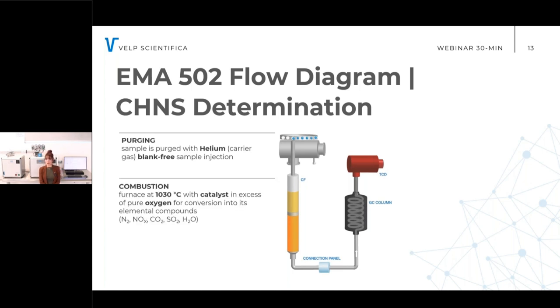The sample drops down the combustion tube at a temperature of more than 1000 degrees in excess of pure oxygen for the conversion into the elemental compounds. In the top of our furnace, during the combustion, the elemental components of the sample are quantitatively converted into gaseous oxidation products, while in the bottom, the formulation of active copper powder placed in the lower part of the combustion reactor completes the process by reducing the nitrogen oxides, NOx, into molecular N2. And then we will have the formation of our reference gases.